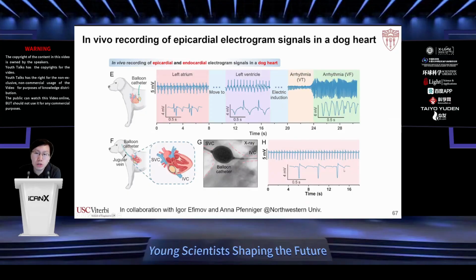And for applications, we use this highly deformable soft balloon catheter for epicardial and endocardial electrogram recording in a dog heart and in a human heart. In this case, it's an in vivo study in a dog heart in collaboration with Dr. Igor Efimov at Northwestern University. So we can insert the balloon catheter to form a conformal contact between the electrodes and the epicardial surface of the dog heart. And also we can insert it into the interior of the heart. This highly deformable catheter is critical to form intimate contact between the electrodes and the complex, rough textured internal surfaces of the cardiac tissue.